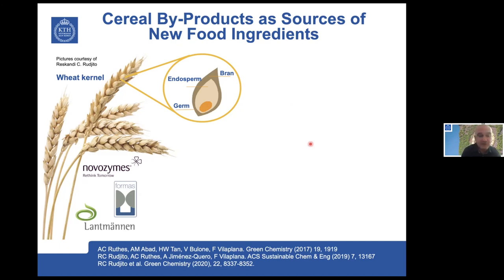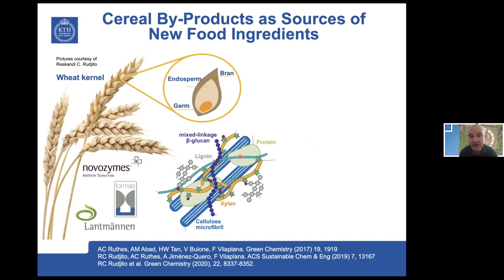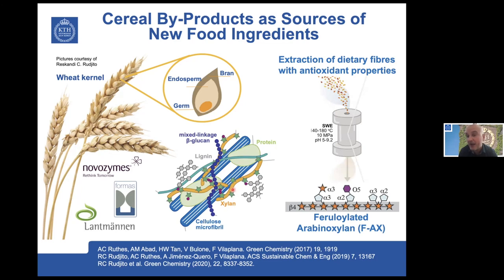The starting point of this project, in collaboration with Lantmännen and Novozymes, was to valorize the outer layer of the cereal grain — the bran — which constitutes approximately 20% of the overall cereal kernel. We were very interested in valorizing particularly the arabinoxylans, the hemicelluloses in cereal bran, which constitute approximately 50% of the total composition. We designed a process using just water at high pressure and temperature — subcritical water extraction — allowing us to isolate and fractionate these feruloylated arabinoxylans with high molecular weight at around 100,000 daltons.